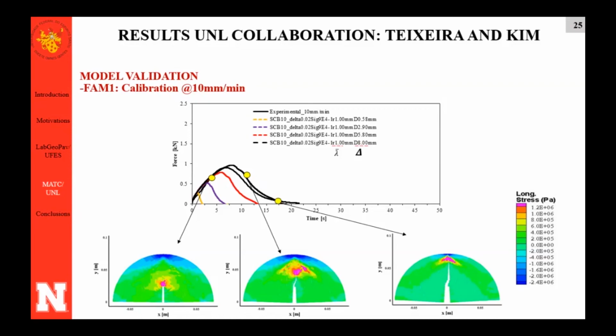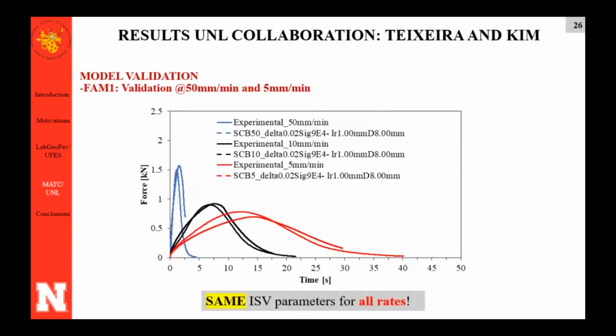And I took now this curve here, the parameters that were valid to fit the experimental data with numerical data, and I tried to predict the behavior in different rates. And that's what we got. And I apologize here, the curve seems the same, but in my laptop, I have dashed lines for numerical and full lines for experiment. But I think you can understand that the results are amazing, right? So the same parameters that I calibrated for one rate, I could predict the behavior of the sample in different rates. So now we're talking about a rate-dependent model with an internal state variable that accounts for the rate dependency of asphalt materials.